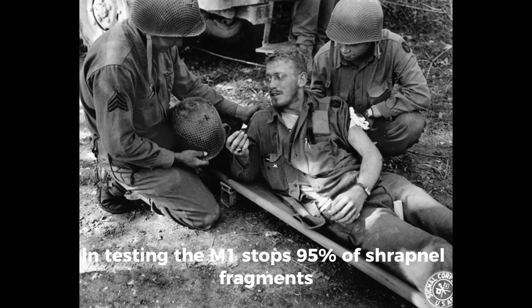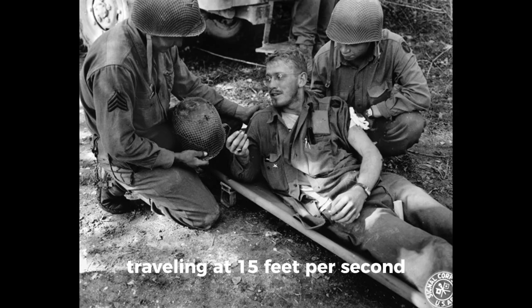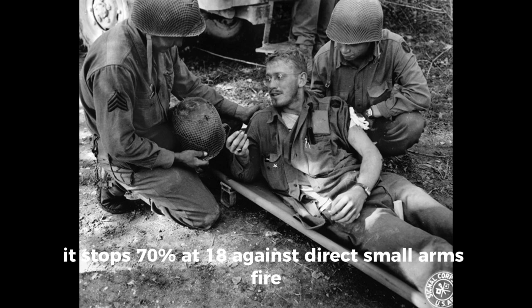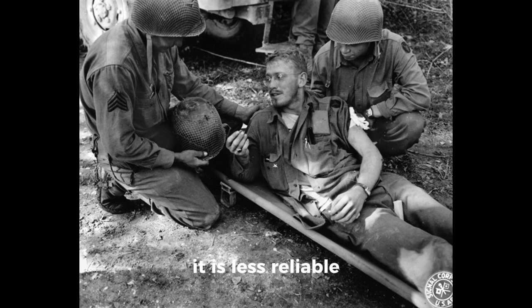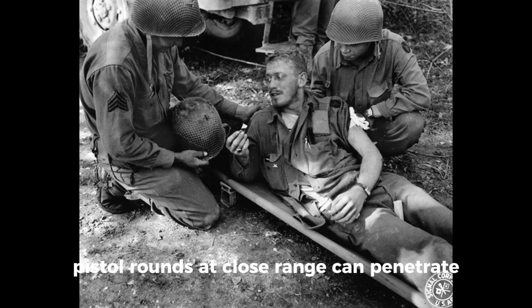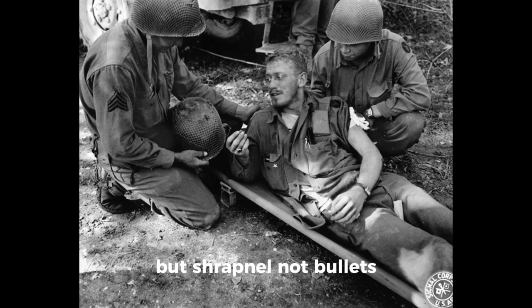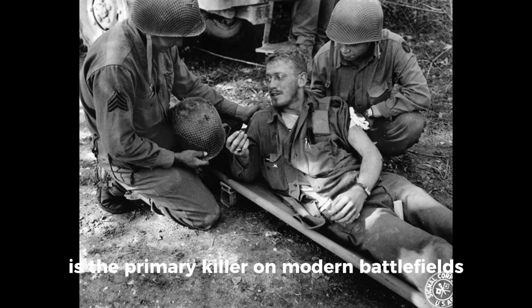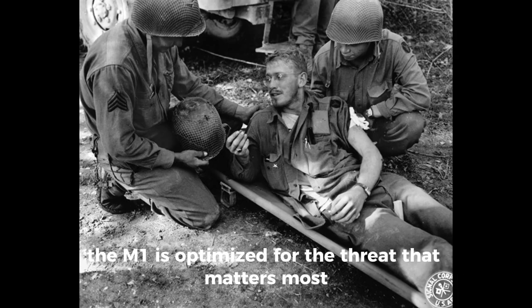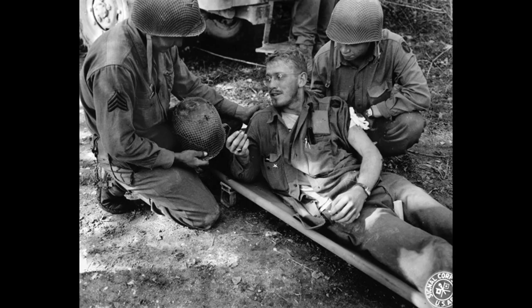In testing, the M1 stops 95% of shrapnel fragments traveling at 1,500 feet per second. It stops 70% at 1,800. Against direct small arms fire, it is less reliable. Pistol rounds at close range can penetrate. Rifle rounds almost always do. But shrapnel, not bullets, is the primary killer on modern battlefields. The M1 is optimized for the threat that matters most.